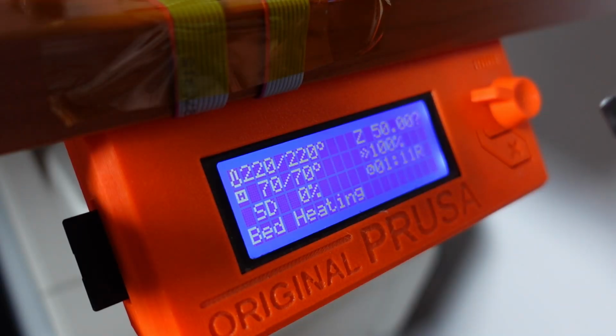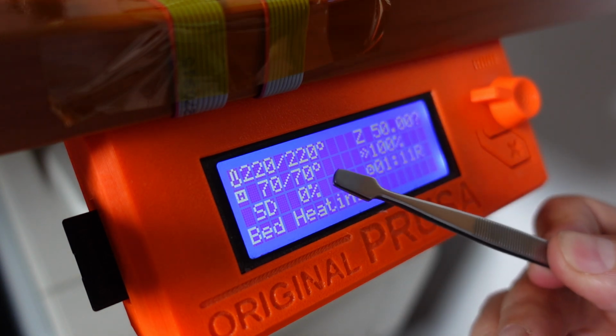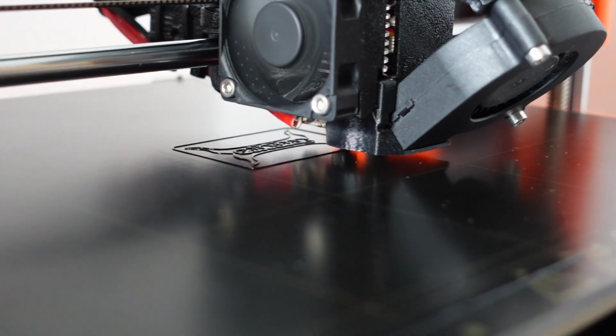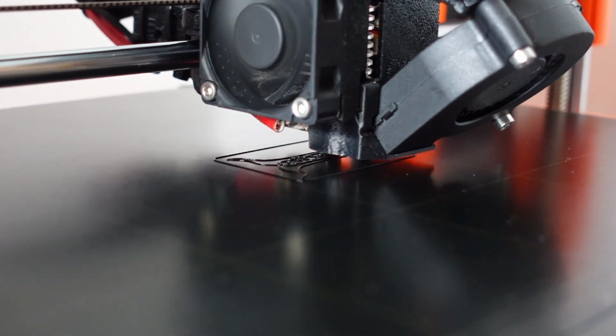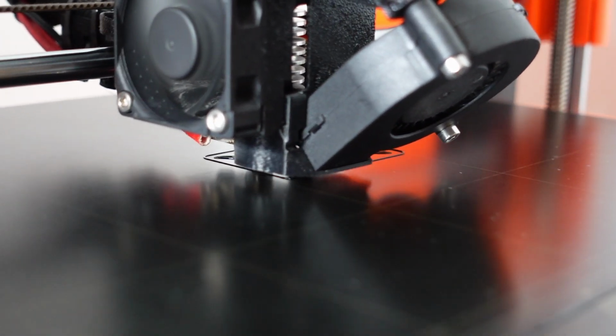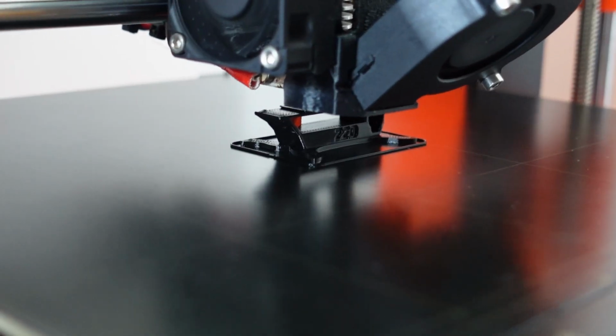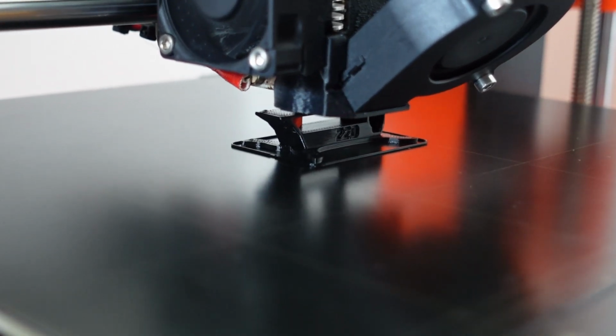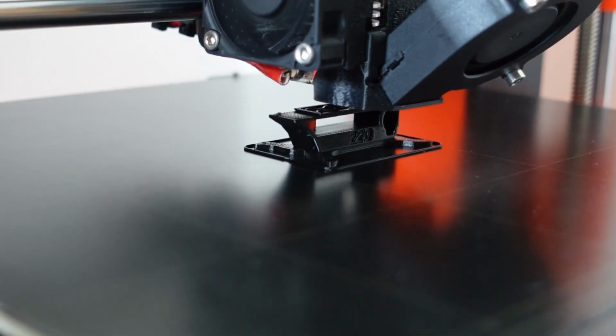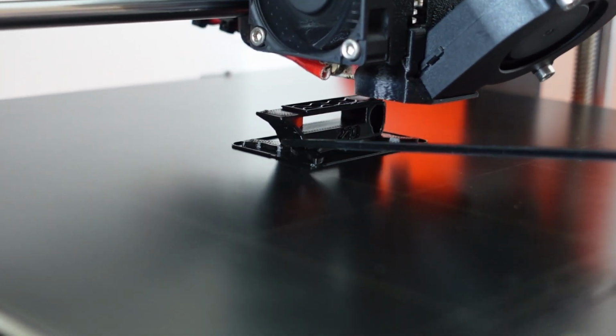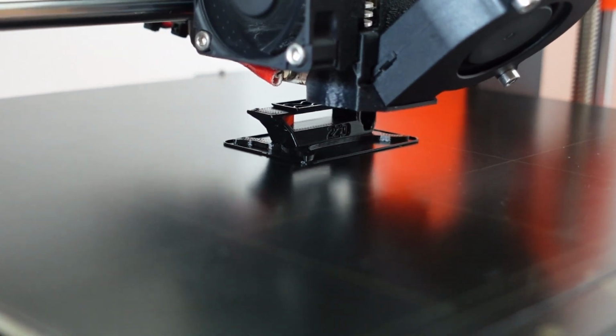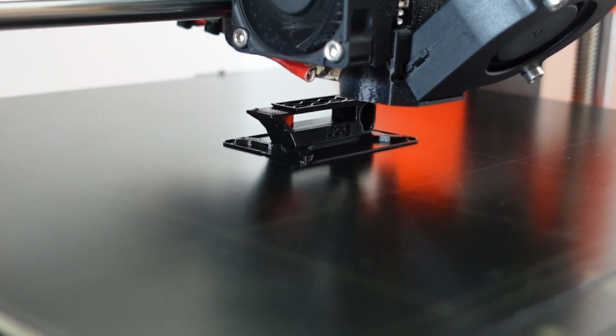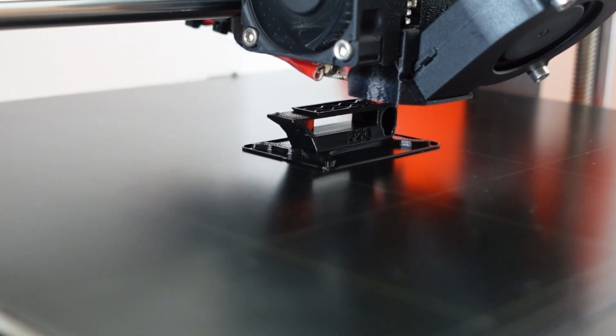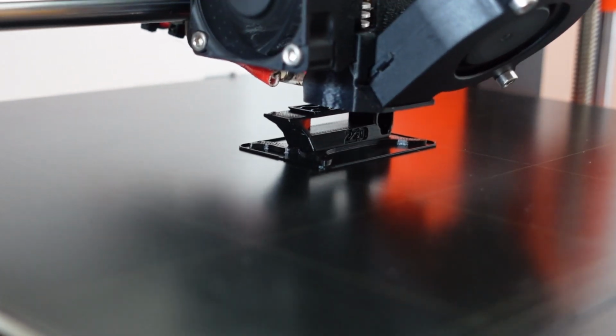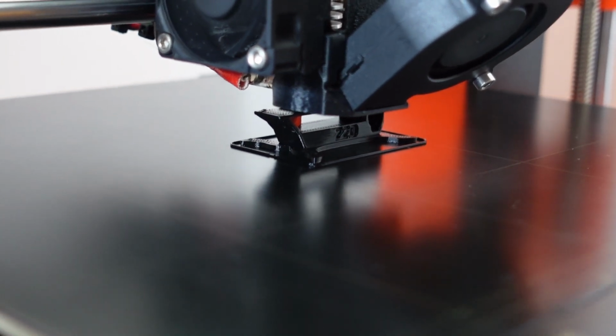I'm starting with a temperature tower from 220 degrees Celsius down to 190 degrees Celsius, and the bed temperature will be 70 degrees Celsius. The first layer is going down very correctly, so I hope I will not have a problem with adhesion. It started with the second element at 210 degrees Celsius, and so far this looks great: absolutely no stringing, the bridge came out perfectly, and also the overhang at higher temperatures, so probably there will be no problems with the lower temperatures. Except I worry a little bit about printing at 190 degrees Celsius. I don't really like to print at such low temperatures, not even PLA.